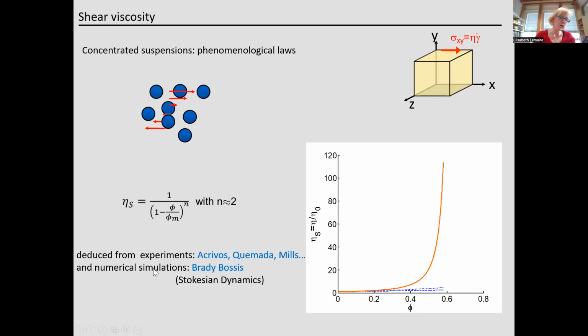You can also refer to numerical simulations, and in particular the first accurate numerical simulations have been made by John Brady and Georges Bossis with the Stokesian dynamics method. And from all these results, experimental or numerical, you can obtain that the variation of the viscosity with the particle volume fraction can be described by this phenomenological law. So the viscosity increases when the particle volume fraction increases, and diverges when the particle volume fraction tends to a critical value, that is the jamming fraction. And the exponent here is close to 2.